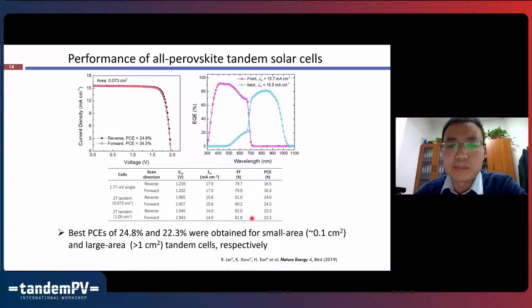But the short circuit current density reduced quite a lot, but it still gave us efficiency above 22%, and that is not too bad at that time. So later we thought a lot about how to really increase the current density of the larger area tandem devices and also the performance of the larger area tandem devices,